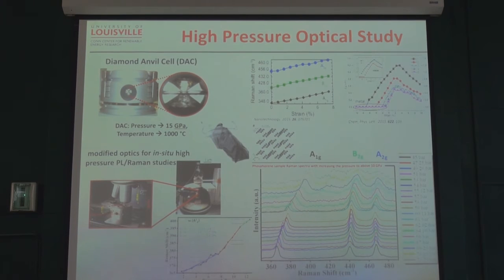Then this is some of the initial results we had for our experiment. This is the Raman spectroscopy, so this is under normal pressure. When you apply pressure, you can see the Raman peak is shifting. All these three peaks, right? We have A1G, B2G, and A2G peaks. They are all shifting under pressure.